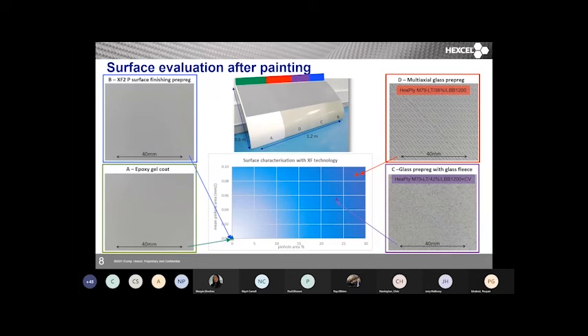You've got a large pinhole area, so you're going to have to do a lot of rework. And also the pinholes are large, so each of them is going to take a lot of attention to fix. Now, we can use fleeces on the surface of components, and we've done that in composites for decades. If you put a standard glass fleece onto the surface of the same prepreg, same reinforcement, yes, you see a benefit. Your pinhole area is down and you're reducing the size of your pinholes. But that's still not paintable. You're still going to have a lot of rework,